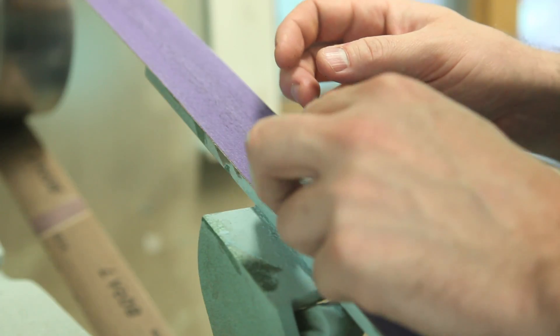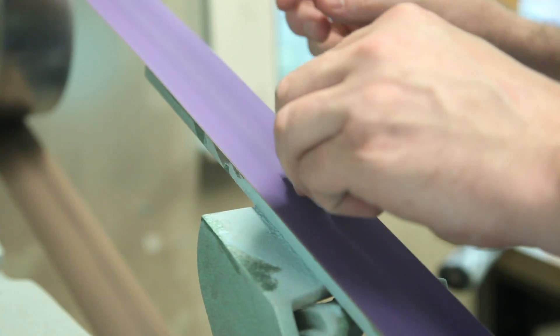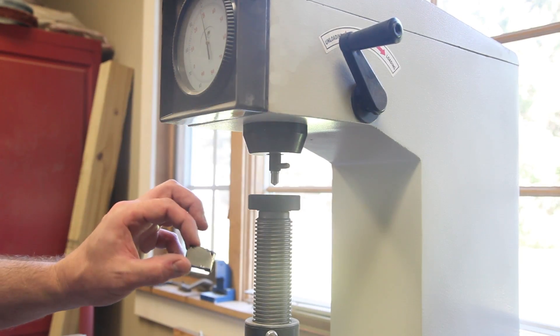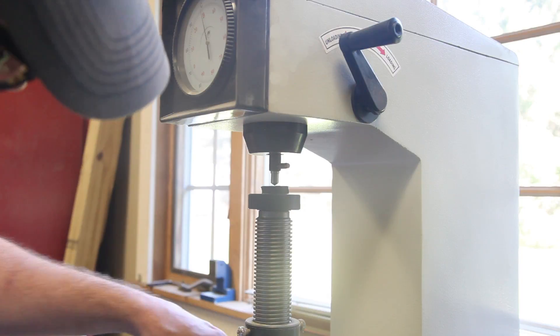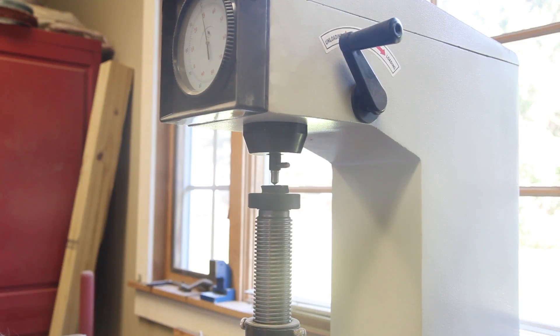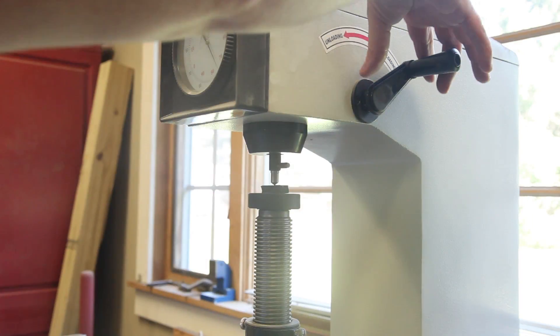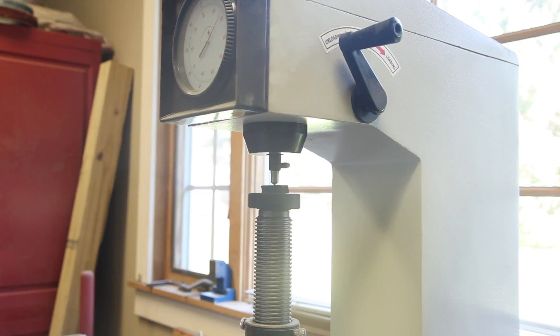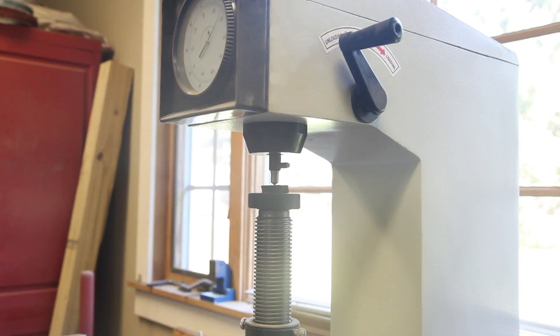Here's our piece. I was able to flatten it a little bit, but in order to test this, I need to kind of surface grind this so that it's flat on both sides. I've just created a basically a flat surface that doesn't have any of that oxidation on it, so that I can be sure I'm testing the metal and not some surface contaminant or something like that. This gives me an idea that the base, just without heat treating, this metal reads at 18 on the dial, so the RC for this untreated is 18.